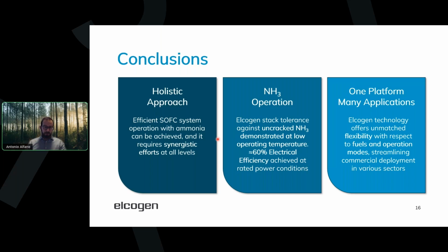Elcogen stacks have been demonstrated to be able to operate with ammonia, with a fuel composition which contains some uncracked ammonia, even at relatively low temperature, close to 600 and 650 degrees Celsius, achieving close to 60% electrical efficiency. Again, a good showcase for the stack platform, which is one, but is able to fit many different applications. Again, possibility to operate with different fuels, different operation modes, so that the same product can really fit a broad range of commercial applications.